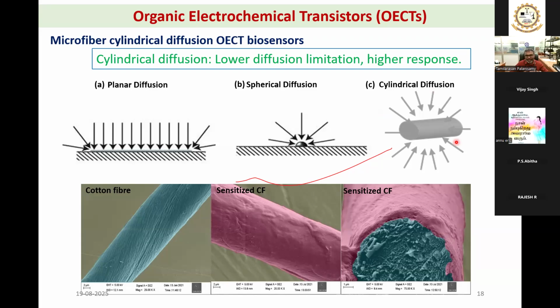Now, if you put an electrolyte, from all 360 degrees, your species will approach the electrode. Now, we just took a very simple approach here. We took cotton fiber. The cotton fiber is typically 10 to 15 microns in size. And we coated the conducting polymer PEDOT:PSS. And you can see here the inner side, the grayish or bluish color is your cotton, and on the outer side you have a PSS polymer. And overall, the dimension is roughly 10 microns.